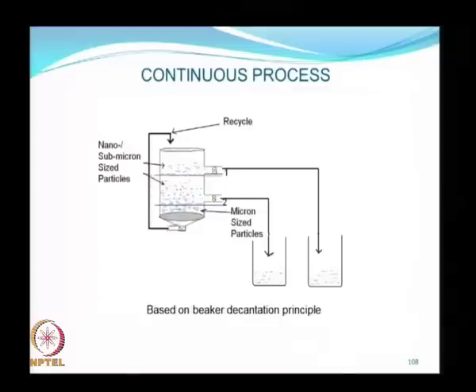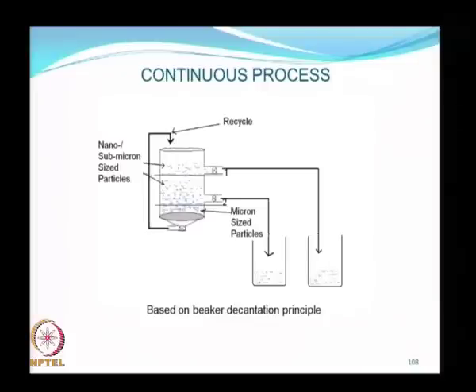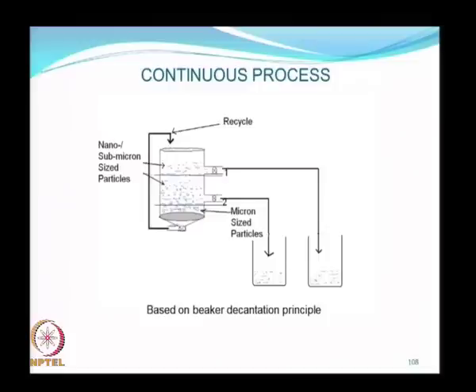In concept, you can actually set up a continuous or semi-continuous flow process to make nanoparticles and separate them by size using a combination of sonofragmentation and beaker decantation. In a continuous process, you expose feed particles to ultrasonics, convert a fraction to nano and submicron dimensions, and drain these off into a collector. The larger particles that are not yet size-reduced will sink to the bottom due to gravity and sedimentation, and can be recycled back into the sonication chamber for further size reduction.